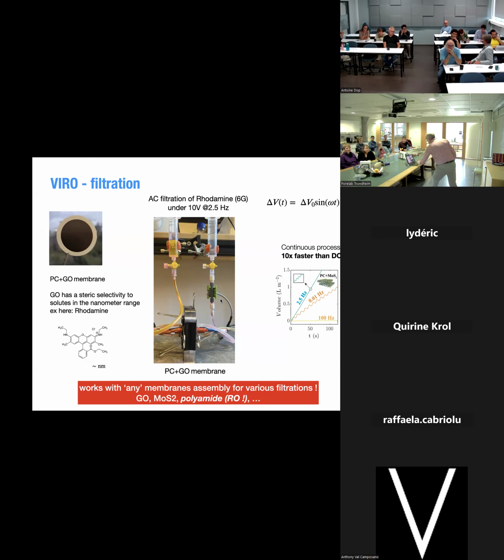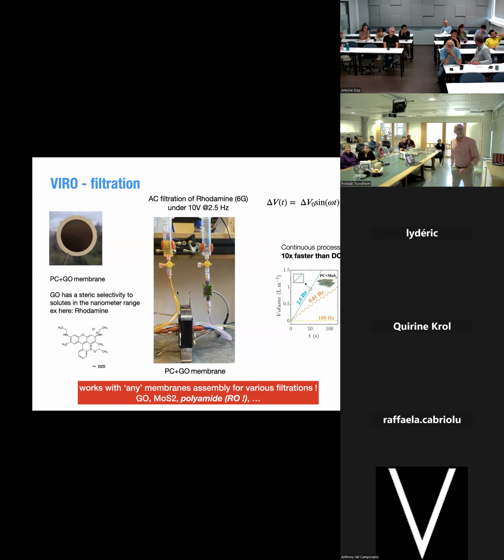If it works, it should be a movie. It's just to show that it actually filters out, of course, because graphene oxide is filtering the stuff and you are pushing it. So under an oscillating voltage, you see it decreasing on one side and increasing on the other. We had to do many films like that because the referee didn't believe it. I have other films which are more explicit, but you see it works and it filters out because there is nothing else it can do.